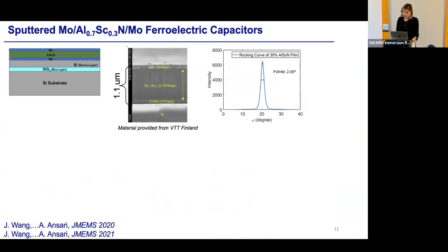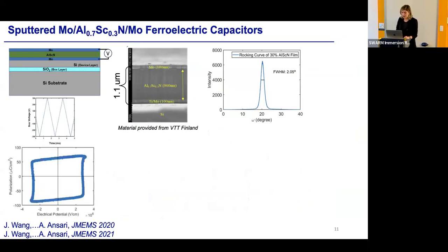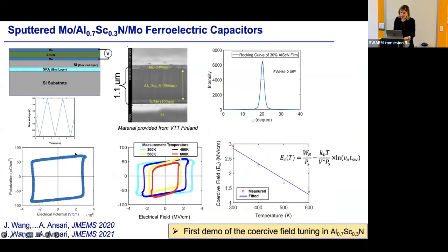So my group has used multiple materials basically to build AlScN resonators and capacitors. So here I'm just showing that basically with the 1 micron thick aluminum scandium nitride, you can observe this very nice box-like structure, and that you can also tune this coercive field by changing the temperature of the environment. As the temperature goes up, you need less of a barrier energy to switch the polarization from, let's say, aluminum polar to nitrogen polar, and you can lower your coercive field by 3x.